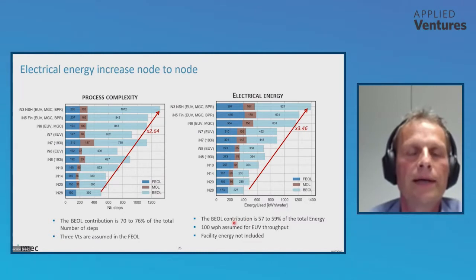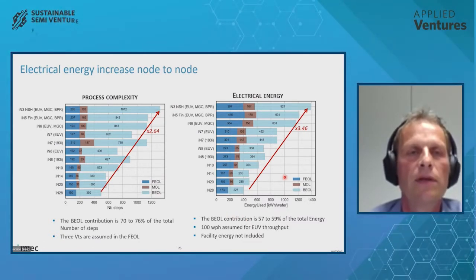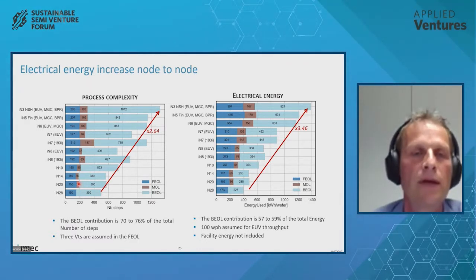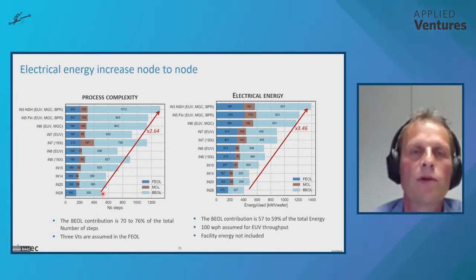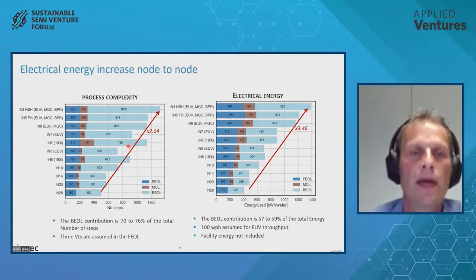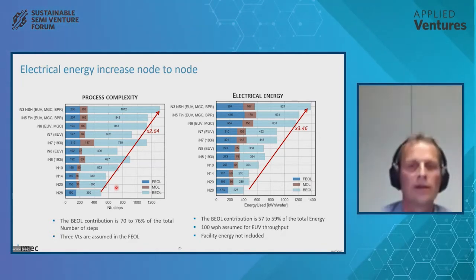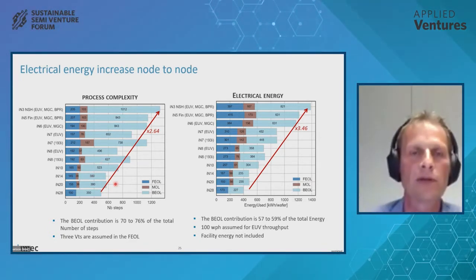So if we then just compare at a high level the process complexity, here you see the front end of line in blue and light blue, the back end of line, and in brown, the middle of line that came into play in the 20 nanometer node. We see that the back end of the line is dominating. That's because of all the metal layers that are introduced. And the increase in complexity is around 2.5 times.